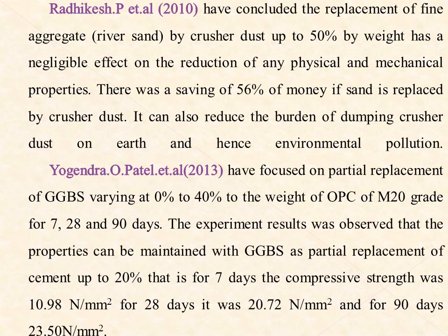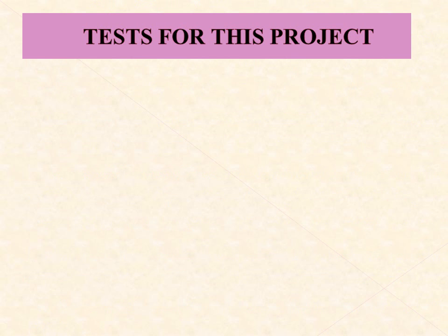Radhikesh.P concluded that the replacement of fine aggregate by crusher dust up to 50% by weight has a negligible effect on the reduction of any physical and mechanical properties. He also concluded that 56% of money can be saved if sand is replaced by crusher dust. Yogendra O. Patel focused on partial replacement of GGBS at varying 0 to 40% by weight of OPC of M20 grade for 7, 28 and 90 days.